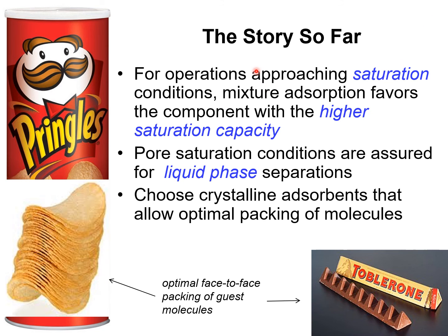Let us summarize the story that has emerged so far. Under pore saturation conditions, mixture adsorption favors the guest component that has a higher saturation capacity. If the feed mixture is in the liquid phase, pore saturation conditions are assured.